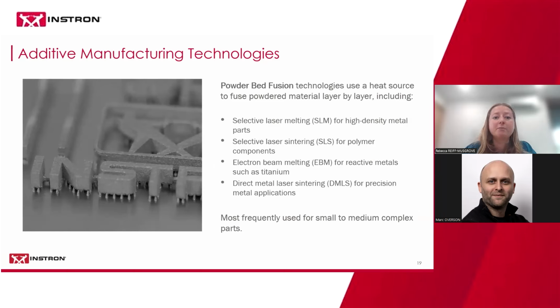Moving on to something we see a lot more for structural parts: powder bed fusion. These technologies use a heat source to fuse powdered material, typically metal but also polymer, layer by layer. As I said, this is a real test of your acronyms if you're in the additive manufacturing world, with SLM, selective laser melting, for high density parts; selective laser sintering, often for polymer parts; electron beam melting, which can be used for reactive materials such as titanium; and direct metal laser sintering for precision parts. We do see this for structural components, and it's most frequently used for small to medium complex parts.